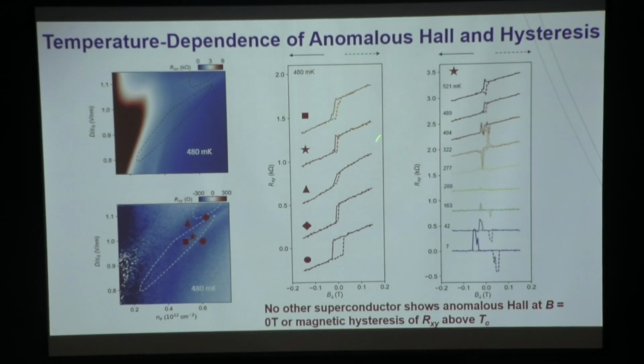And when you cool down the temperature and park the sample at the star position, which is inside the SC1 region, you find that from this behavior, you get the slope corresponding to the normal Hall plus this anomalous Hall due to valley polarization. When you cool down, eventually both of them will go to 0, because when you get into the superconducting state, it just gets shorted, right? Rxy becomes 0. But you still have these spikes when the superconductor is switched by the external magnetic field from polarized in the K valley to polarized in the K prime valley. And this is basically the spikes you were seeing in the Rxx scanning inside the superconducting state.